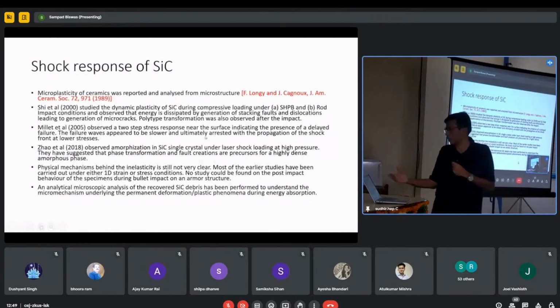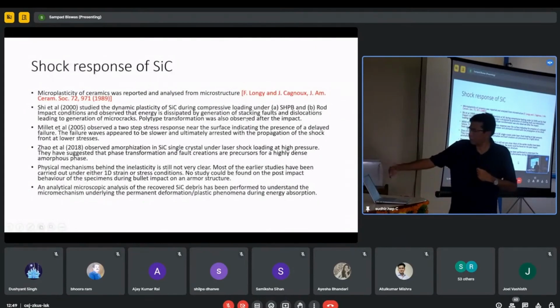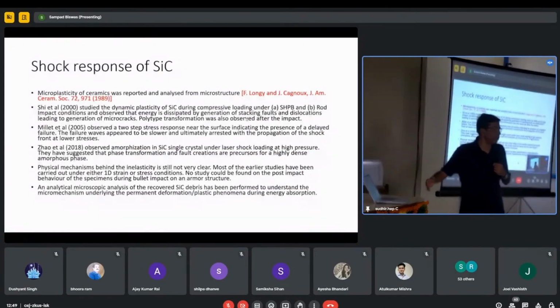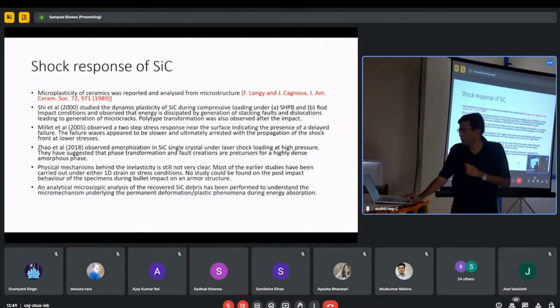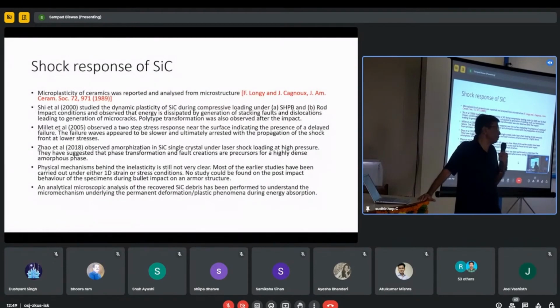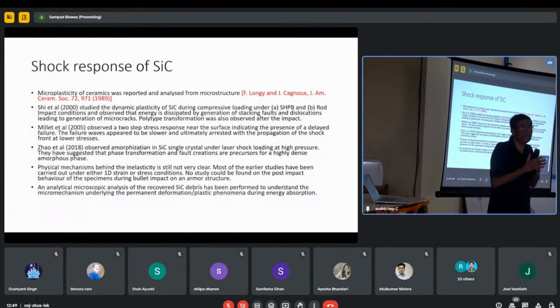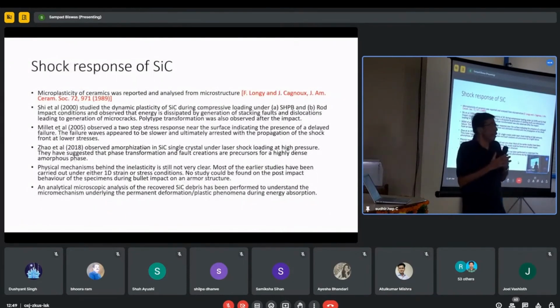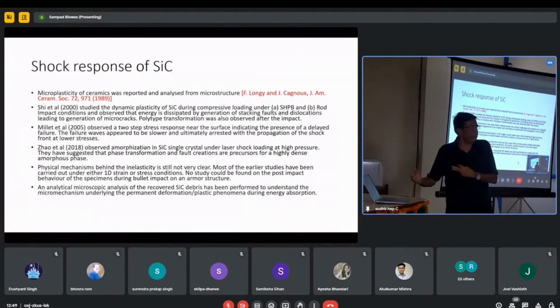Then some people have also analyzed the dynamic plasticity of silicon carbide during compressive loading. So these are the previous works I wanted to mention to you. Lastly, some people have found that amorphization takes place. That means when you are hitting it with a bullet, when you are giving it extra shock pressure, crystalline to amorphous phase formation occurs, and from there recrystallization also takes place. These were the mechanisms, and some people have observed them. We will also show you how it happened in our case.